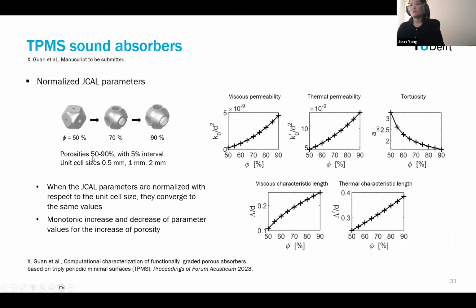So we conducted this simulation for the porosities from 50 to 90% with 5% interval, and for different sizes of the unit cells. And we generated a data set of this porosity and also unit cell size. And in this graph, you can see those transport parameters: viscous permeability, thermal permeability, tortuosity, viscous characteristic length, and the thermal characteristic length. And we found that if we normalize these JCAL parameters to the size of the unit cell, they actually converge to the same values. So we normalize the viscous permeability and the thermal permeability by the square of the unit cell size D, and the viscous characteristic length and thermal characteristic length by the unit cell size D.